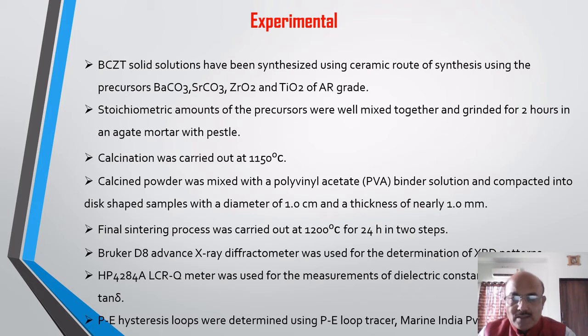The calcination was carried out at 1150 degrees centigrade. The calcined powder was mixed with PVA binder solution and compacted into disc-shaped samples with a diameter of 1 centimeter and a thickness of 1 millimeter. The final sintering process was carried out at 1200 degrees centigrade for 24 hours in 2 steps.